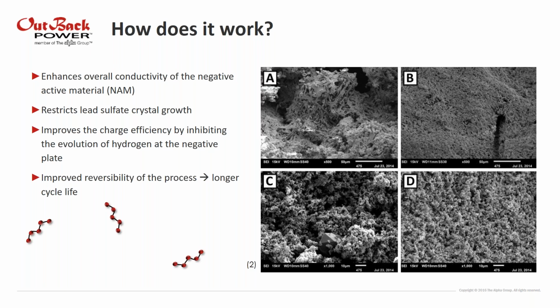Conversely, with square B, you can see that those crystals are much smaller, they're much more uniform, and it shows a tight crystalline arrangement and a well-structured surface. So obviously, B is an electrode with a nanocarbon additive in it. So those smaller crystals, the more uniform crystals, they're much easier to dissolve and force back into being the lead and lead dioxide. So that's what I mean by it restricts that lead sulfate crystal growth.